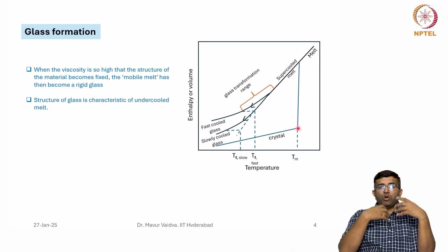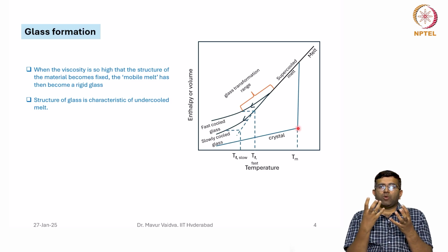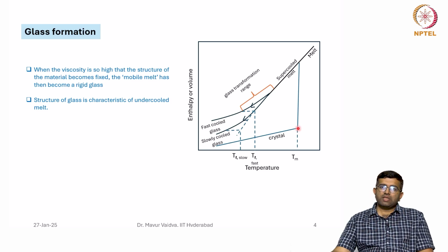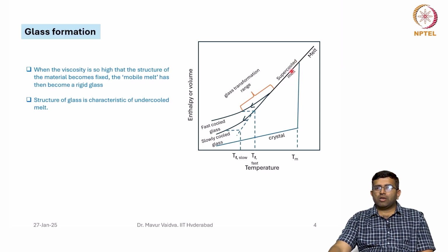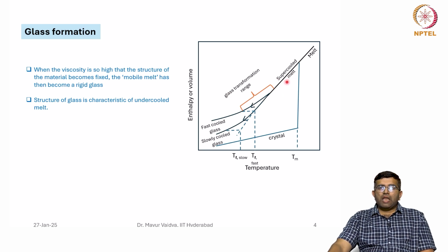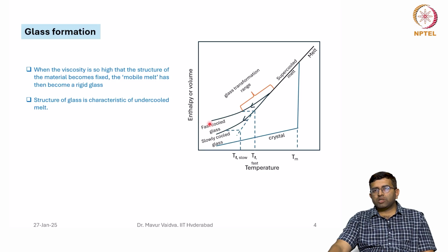Now, suppose you do not allow that much time, and you cool down this liquid very fast. Then instead of going for crystallization, it keeps cooling down, and the volume or the enthalpy begins to decrease in a continuous manner. Let us say below a certain temperature, you will see this kind of a transition happening, below which it becomes solid, so much so that it no longer resembles a liquid in mechanical or physical behavior, but it is glass, it is like a solid.